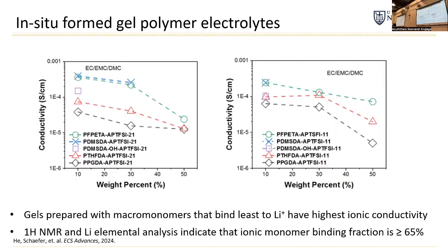And we first looked at the conductivity of these gels. What we found was uniform across the board. We looked at a wide parameter space. We looked at the weight percent of the total amount of monomers in the solvent, so going to higher weight percent means a lower amount of conventional solvent. We looked at changing the amount of ionic monomer in there. And then the chemistry of the macromonomer was our main variable.